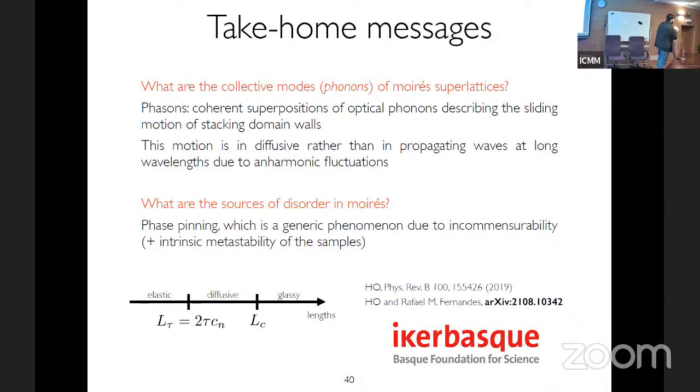Now, why am I invoking this picture where I'm starting from a floating phase and then I start to contract? The reason is, we have the moiré period, the domain wall width, which is the competition between these two energy terms in the free energy, and then the interatomic distance. If the domain wall width starts to be comparable with the interatomic distance, then you're in trouble. Now, what is the domain wall width? It's several nanometers. Why? Because the van der Waals interaction is very weak, whereas graphene is very rigid. So I think these ideas and this continuum description are still valid here.